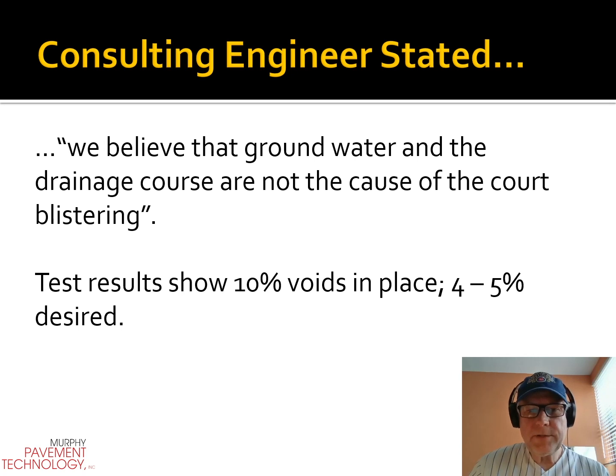A consulting engineer stated that they thought it was groundwater that caused it, but the test results showed that there was 10% in place air voids in the asphalt when 4 to 5 is desired. Trouble will begin if it goes above 8% air voids. So probably want to target no more than 7%. Average should be 5 to 6% air voids.